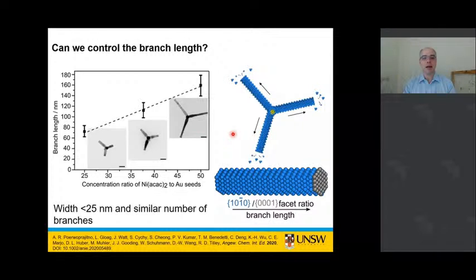And with these reactions, Agus could really get great control, particularly of the length of the arms. If you just change the concentration of how much gold seed he put into the reaction compared to how much nickel precursor, if he had a lot more nickel precursor compared to the amount of gold seed, he was getting longer and longer arms.